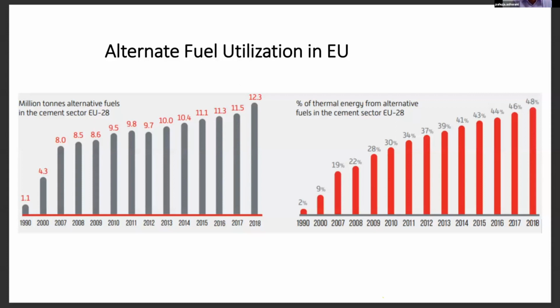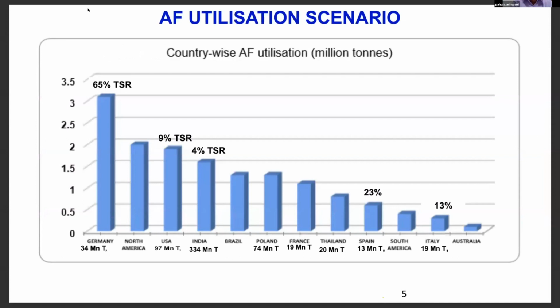Can we go to the next slide, please? As we see here, for different countries, for example, in Germany, the thermal substitution rate is around 65%, and Germany utilizes nearly 3 million tons of alternate fuels. Whereas in India, for a production capacity which is almost 10 times that of Germany, Germany has a production capacity of 34 million tons, India 334 million tons of production, it stands at only a 4% thermal substitution rate. But as we see, nearly 1.6 million tons of alternate fuels is utilized.